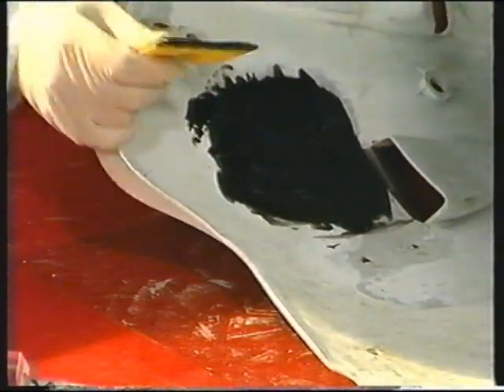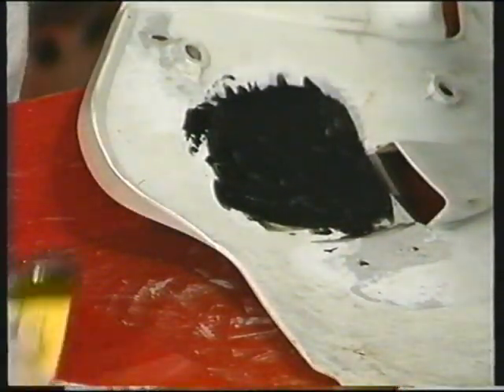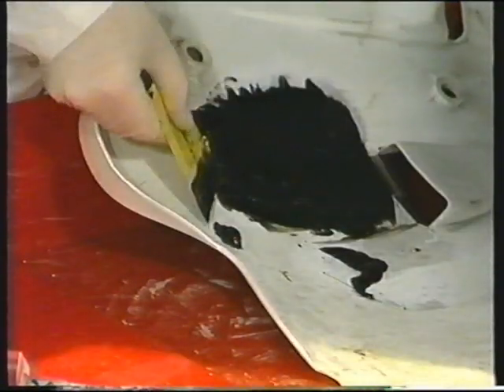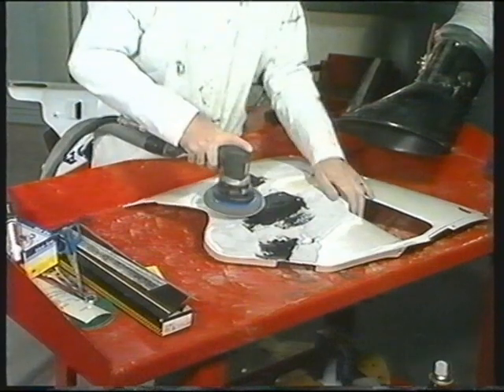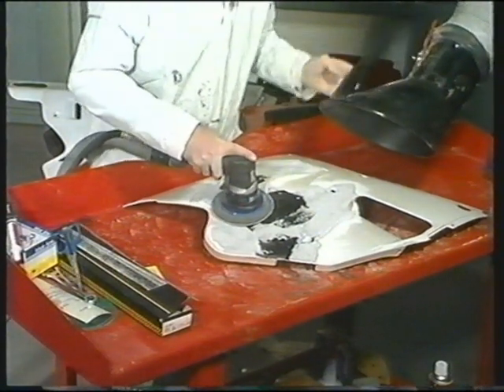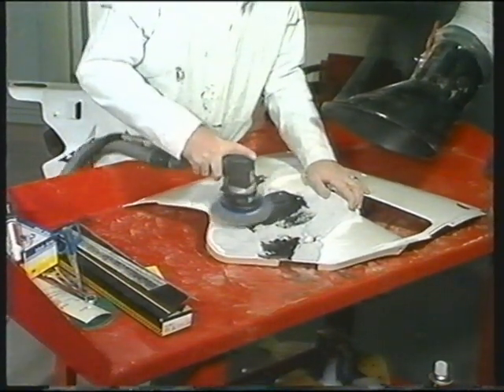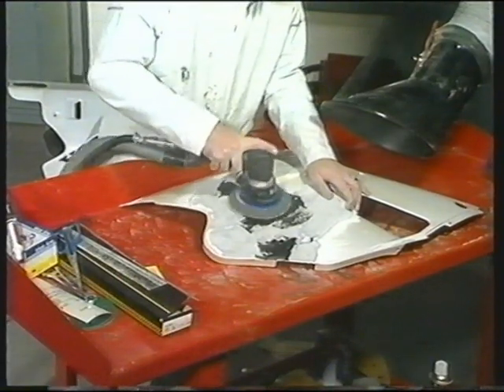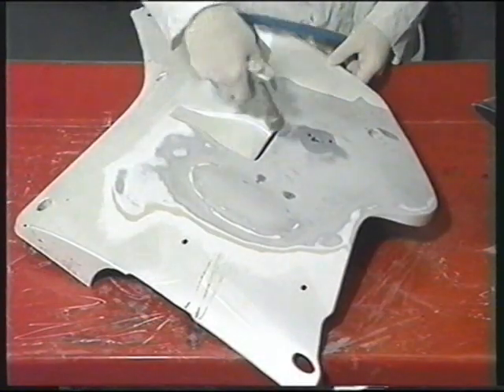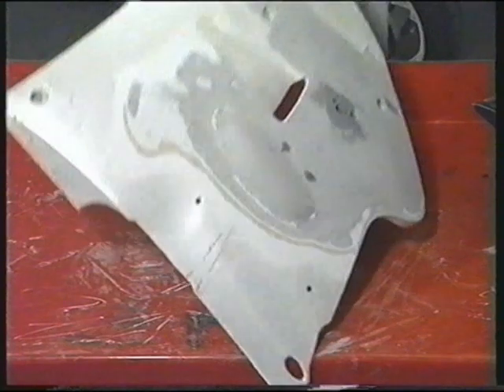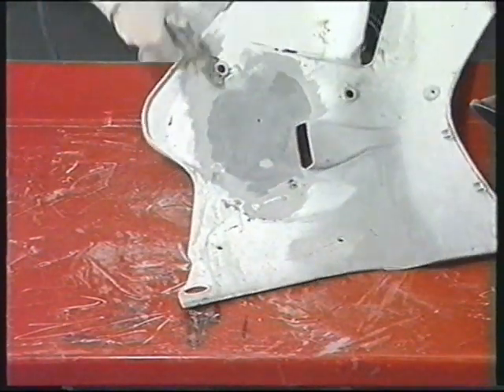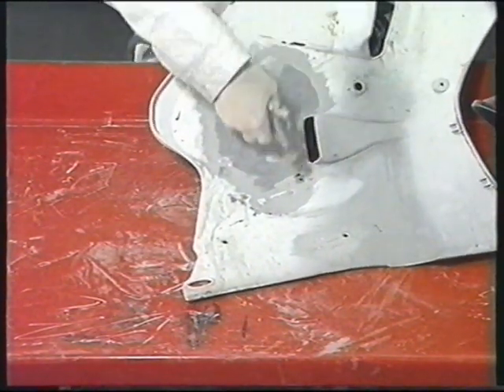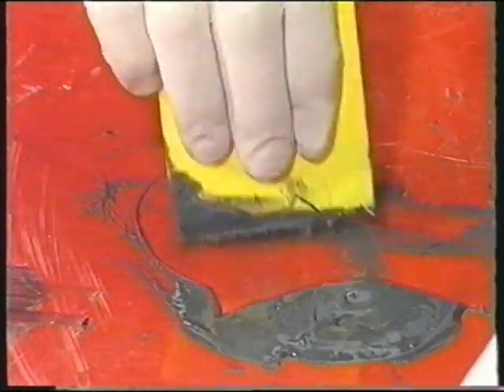Minor damage requires no gauze. The adhesive is applied like a filler in these areas. The material must be cured for 2 hours at 23 degrees Celsius or for 30 minutes at 60 degrees Celsius using infrared or an oven. The excess adhesive is then sanded off. Any dust is blown off prior to filling with the same 3M flexible parts repair material as was used on the welded repairs.